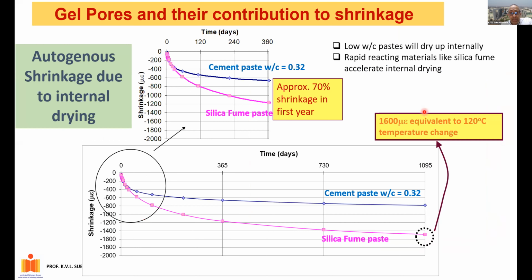the retaining wall. Now, to explain shrinkage, if I take a piece of cement paste, even if I seal it, it basically would start shrinking. This is the amount of shrinkage that I would get if I take normal cement paste. But if I now start adding densifiers like silica fume, then I get a lot more shrinkage. How much shrinkage can I get?